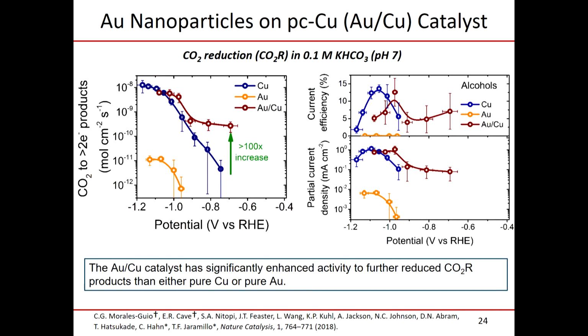And so on the left plot here, I'm showing you how many CO2 molecules are getting reduced to these greater than 2 electron products, which are oftentimes more attractive in this scheme. If you look at pure gold, it's not very good. If you look at pure copper, it's certainly decent. That's the data I was showing you earlier. If you put this gold on top of this copper, you get a 100-fold increase in the reaction rate at these lower overpotentials. And what are you making? You're making predominantly alcohols like ethanol and propanol.